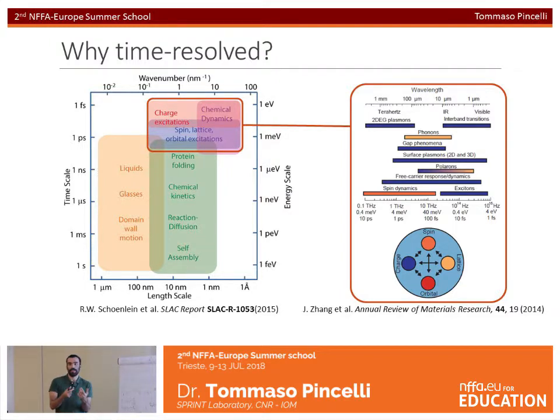But competition also means that the energy scales of the ordered phases are very close to each other, and so it's very difficult to distinguish from equilibrium spectroscopy. But the interactions that give rise to an ordered phase can be of very different energy scales, and thus order the system on much different time scales. So you can distinguish on this scale. I will try to give an example of this later on.